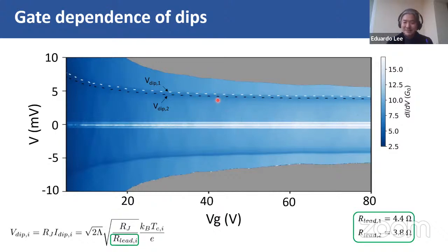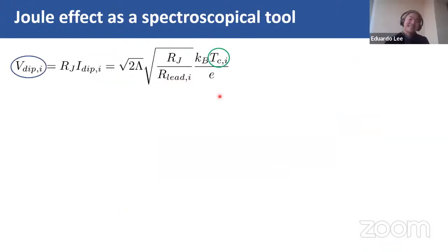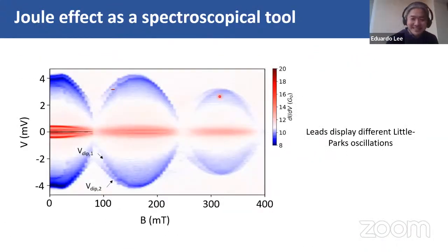But if we make them less symmetric, one, let's say, with twice the length of the other, then we can really see that the splitting of the two dips increases. So we're quite confident that at this level, for zero magnetic field, this asymmetry here is due to geometrical reasons. Okay. Now, moving on to the second part. So why do we now say that these changes or the different oscillations are due to the coherence length and not for geometrical reasons? Well, first of all,